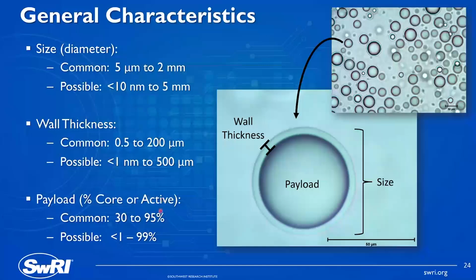The thinner you go, the more fragile the shell, the less protective properties, the more transmission of oxygen, water, or other outside environmental factors. So 95% is kind of a reasonable top end. 80 to 90 is more common with some of the emulsion-based processes. But what's possible, again, you can go less than 1% and above 99%, but there are massive trade-offs when you get into those extremes.